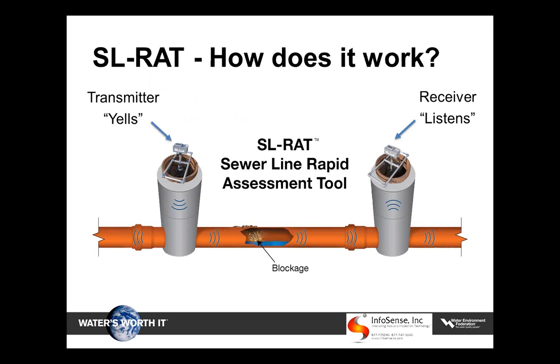The product, the Sewer Line Rapid Assessment Tool, or SL-RAT's objective, is to help wastewater collection system operators obtain condition assessment information, and specifically blockage condition information, about their smaller diameter lines, specifically focusing on those in the 6 to 12-inch diameter range, which on average we've found comprise approximately 90% of pipes in the U.S. and also are where approximately 90% of SSOs tend to occur.